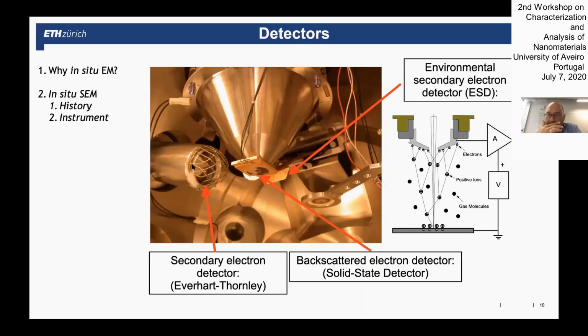But when you introduce gases, then you have to switch off this Everhart-Thornley detector, because this one has quite high electric fields for acceleration of the secondary electrons. So this one is deactivated, but you switch on another detector. That's this golden plate here in the back. It's called gaseous secondary electron detector because it's used when you have gases inside the microscope.